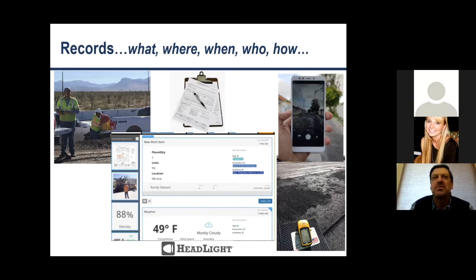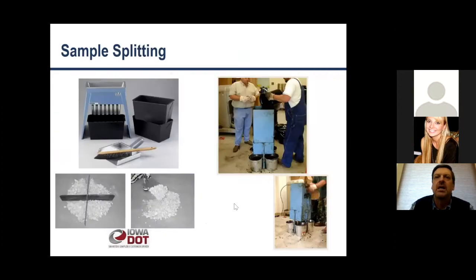So if you do sample from the mat, there are techniques again to minimize some of the issues that you see in this mat here with the segregation. I brought up splitting earlier. Regardless of whether it's binder or aggregate or hot mix, when you're splitting your materials, the goal is to get representative samples that are of the appropriate size. There are different techniques that can be used.